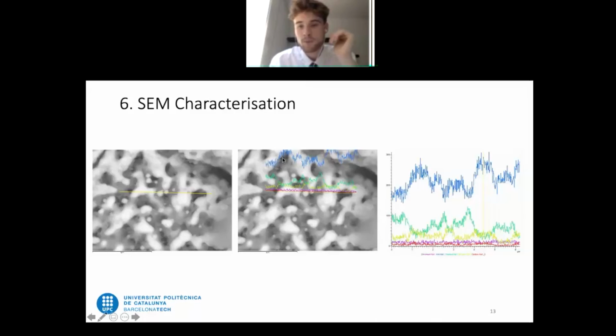Here we can see the spectra that has been produced, and down here is the legend of what each of these colors correspond to. The blue spectrum represents iron, the green spectrum represents titanium, and the yellow spectrum represents oxygen. Referring to this middle image, in the brighter areas there's a significant spike of iron and very low amounts of titanium and oxygen. Then in this dark patch there's a much lower amount of iron, with an increase in titanium and a fairly standard plateau of oxygen as well.